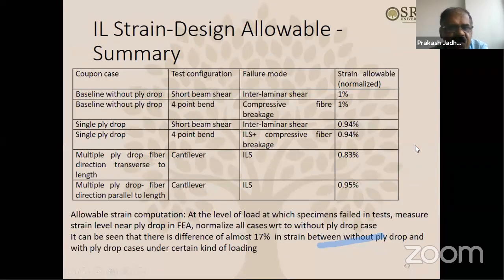Okay, so ultimately to summarize this ply drop testing and analysis that we did. So as you can see, if you normalize the values, let's say for the baseline specimen without ply drop, you have, let's say, 1% strain. So normalizing this basically. Under short beam shear and interlaminar, the failure mode is interlaminar shear, the test is short beam shear. And if you take another baseline specimen for 4-point bend and compressive kind of compressive fiber breakage kind of failure, and let's say the strain allowable is again normalized to 1%.